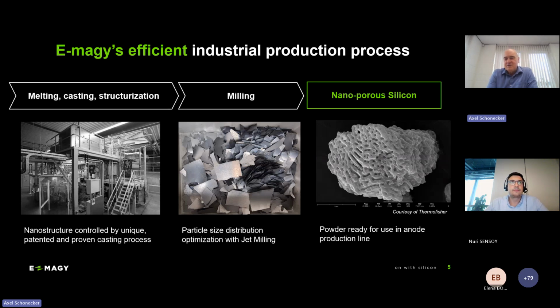That is a particle that is a typical particle size of 5 micron. So compatible with, for example, graphite that is used in anodes. And this material can also be used in water-based slurry processing, in a coating on the equipment that is existing in battery manufacturing lines. But of course, silicon has a big challenge, and that is the swelling that silicon undergoes when it lithiates. And that is why we built in this nanoporous structure.